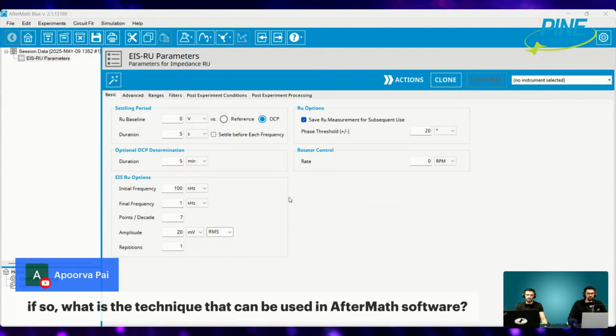what you're going to do is, the potentiostat has, I assume you have a bipotentiostat if you're doing a ring, right? So there's a red and an orange lead. That's the working electrode 1. There's a blue and a purple lead. That's the second working electrode. Normally, the second working electrode, the blue and the purple, is connected to the blue brush, the bottom brush on the MSR rotator, or if it's a WaveVortex, I forget which side it's on. Anyway, the blue brush. And the red and orange cables from your potentiostat connect to the red brush, which is the disk. So if you want to just calculate the RU of the ring, ignore the blue cable, leave it loose, plug the red cell cable from your potentiostat into the blue brush. Now you are just studying the ring. The other two electrodes remain the same, counter and reference. Whatever those are in your solution, your cell, I assume, leave those the same.